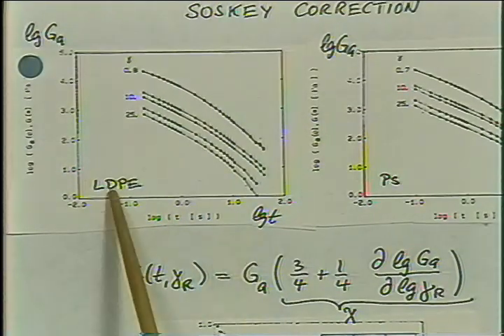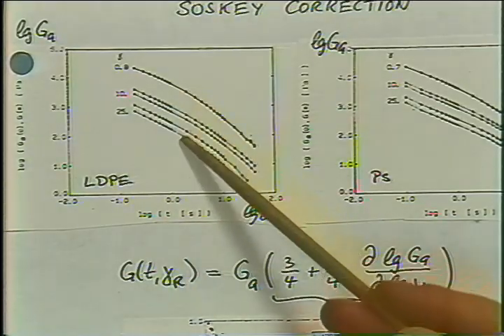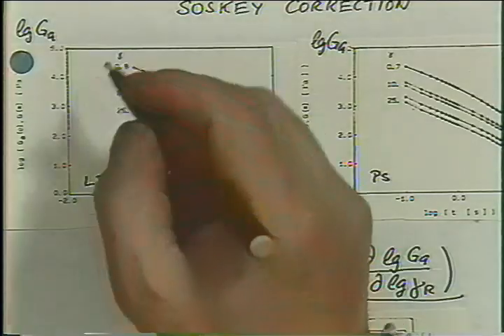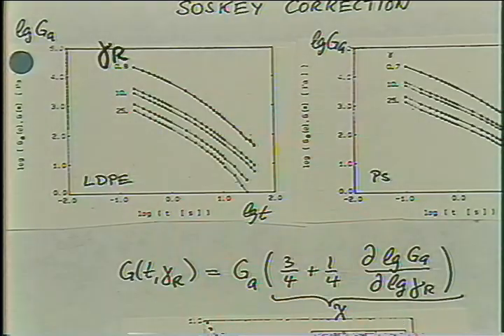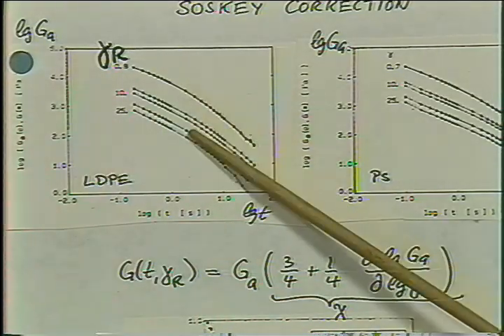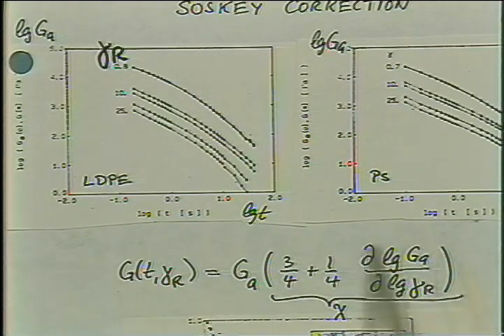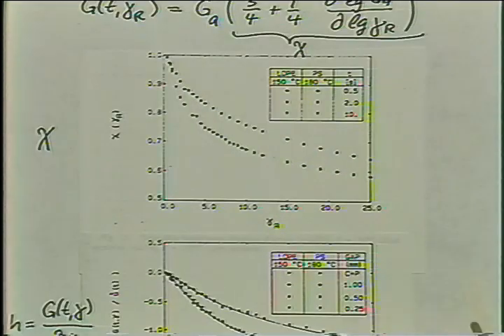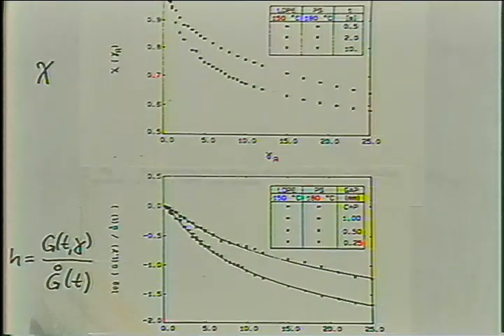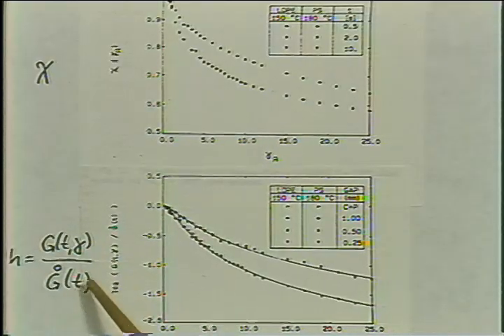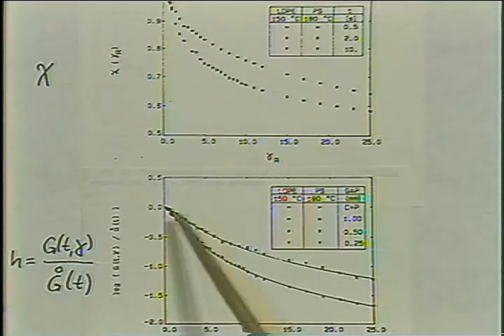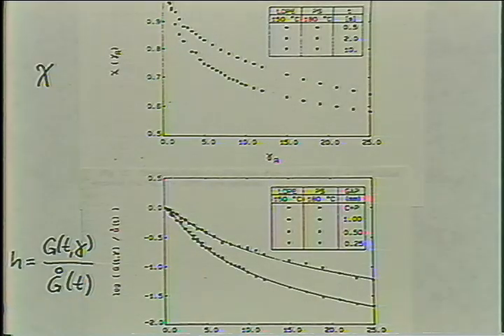And with that, Soskey was able, this is the last figure I want to show here, Soskey was able to measure the apparent modulus of a low-density polyethylene and a polystyrene as a function of time at different strains. This is the strain at the outer edge, gamma R here. This is the strain, small strain, large strain. He uses his correction function, and from that he gets then the ratio of the relaxation modulus divided by the linear relaxation modulus, and this is the function which Osaki had plotted.